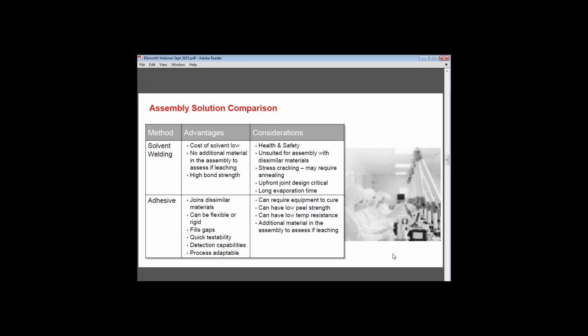Quick testability. With most adhesives, you can test them immediately, so that in this realm would look like possibly doing a pull or leak test immediately in line. Also, with considering quality inspection, most of the adhesive technologies do have detection capabilities like fluorescence, so that you could see did the adhesive get on the part and did it get in the entire area of the part. So in the case of a tubing and connector joint, did it go all the way around 360 degrees? And very adaptable to your process, and we're going to highlight that as we move into the data.